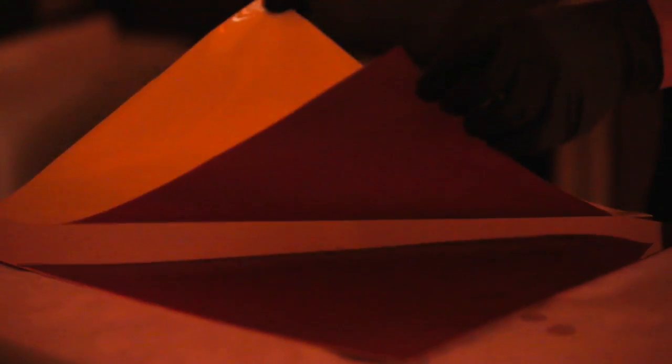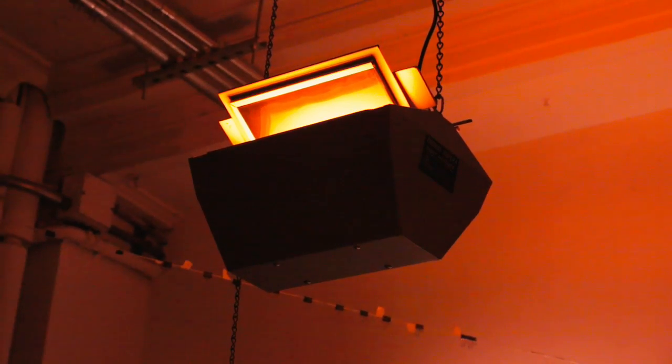Then you dampen that gelatin sheet and you attach it, lay it down onto a chemically clean rosin aquatinted plate of copper. That's dried for about a half hour. And then that is put into a bath of hot water where it is termed developed, where we melt the gelatin, it releases the paper.